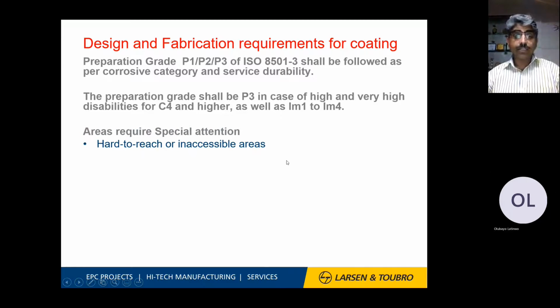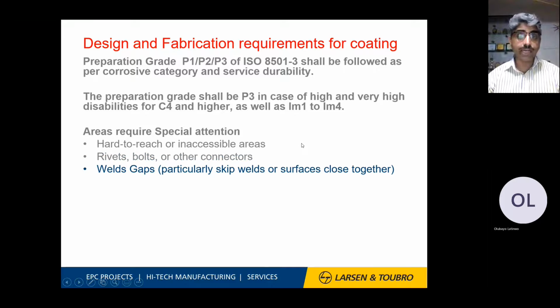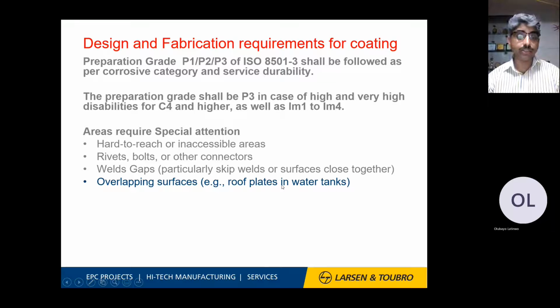Areas requiring special attention based on the ISO standard are hard to reach or inaccessible areas, where blasting or mill scale removal is the challenge. Other are the rivets, bolts, and other connections where crevices are going to be formed. That is also a challenge for giving more life to the coating, as we saw in the pictures before. Other is the weld gaps, as in the offshore platform. Weld is the area where, if you apply the paint, it is prone to corrosion because the paint does not stick to that particular surface very tightly. It is not adhered to the surface.